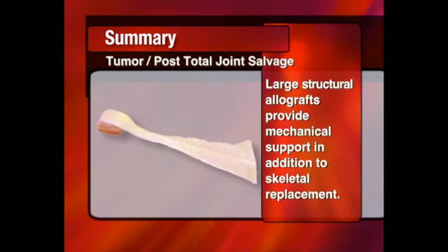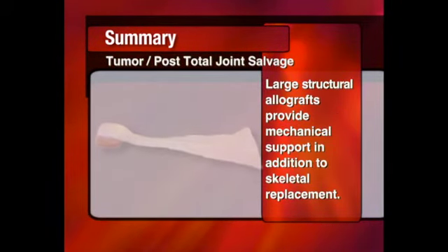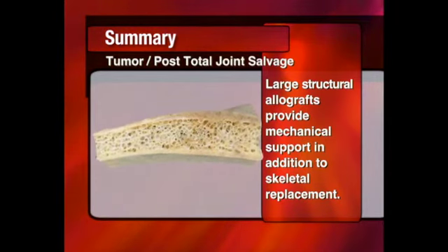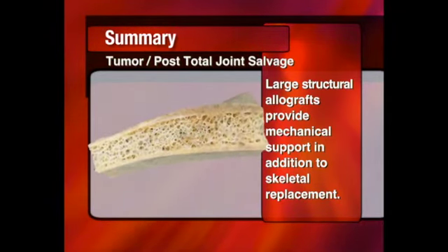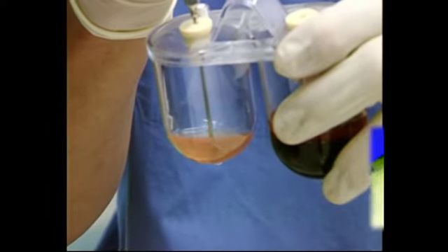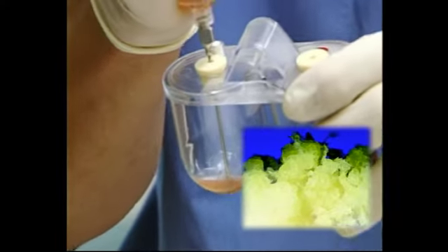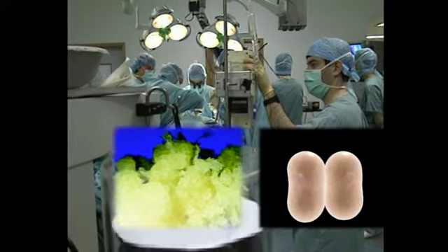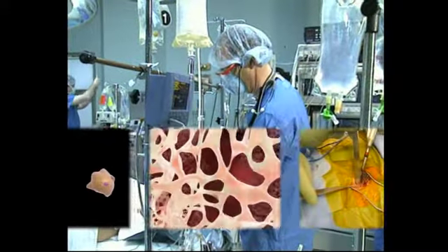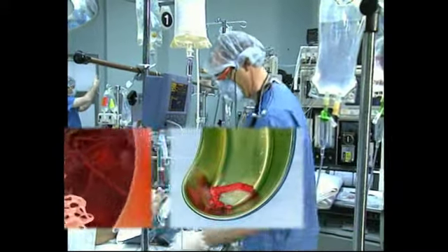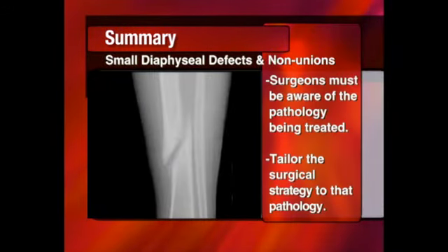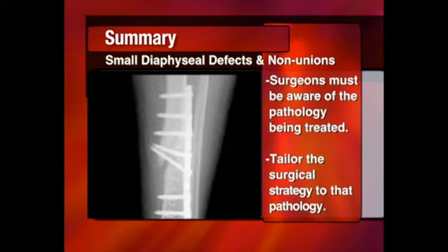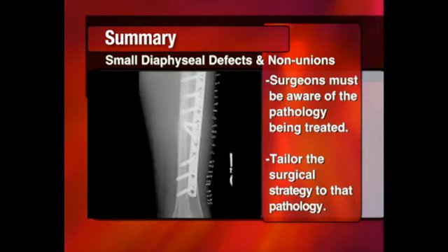For tumor or post-total joint salvage, large structural allografts are often indicated to provide the necessary mechanical support in addition to the skeletal replacement. In an effort for these large allografts to heal at their host allograft junction, inductive factors in combination with cellular substrates and conductive materials can be utilized, as can a cancellous autograft that would provide similar material properties. For smaller diaphyseal defects or straightforward non-unions, surgeons must be aware of the pathology being treated and tailor the surgical strategy to that pathology.